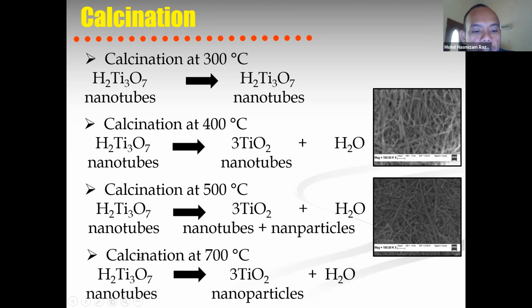And then after calcination at 700 degrees C in this study, we can obtain 100% titanium dioxide nanoparticle. So that means the nanotubes of the sample transform into nanoparticle due to the heating at higher calcination temperature.